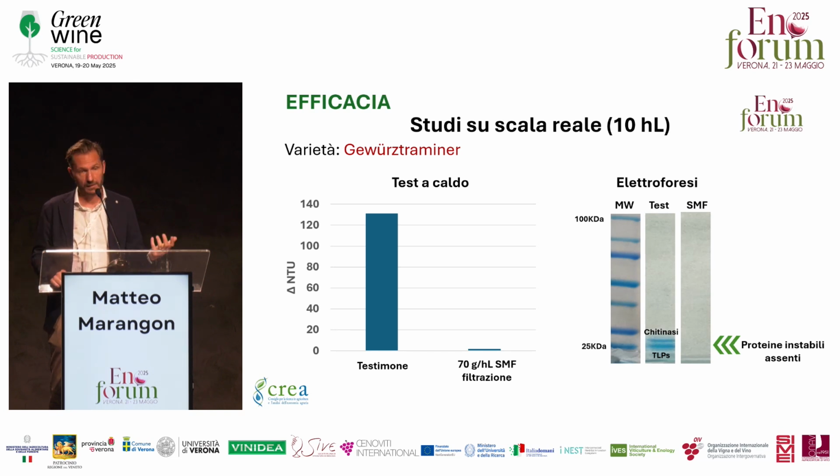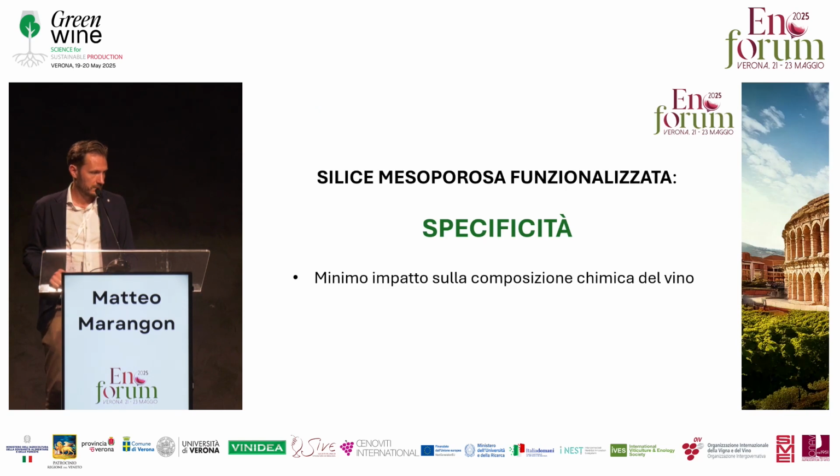Here, electrophoresis is used to visualize the proteins in the control, in the test wine, before and after treatment. Here you see that the bands of the pure proteins have disappeared, which means that the silica retained those proteins also during the filtration process. Here we have a number of data produced over the course of time in order to try and test whether it is effective, this material. Well, we are convinced that it does work. It is effective in a way that is very similar to that of bentonite.